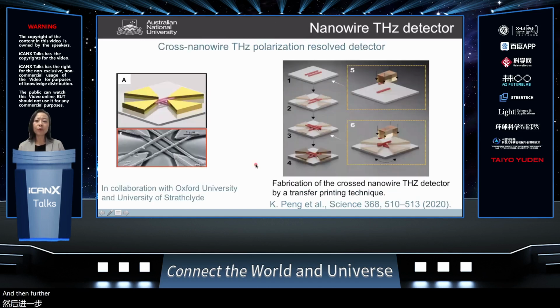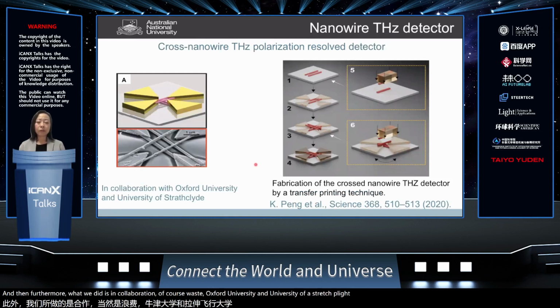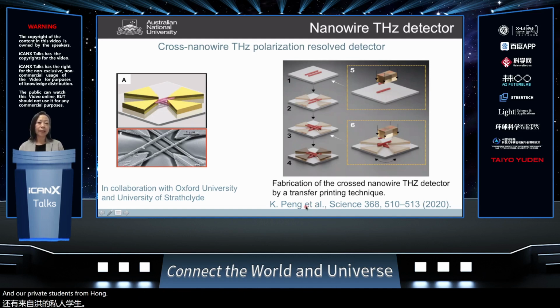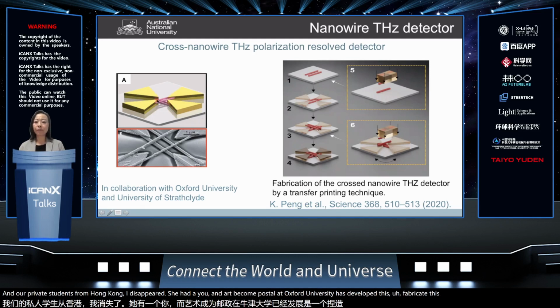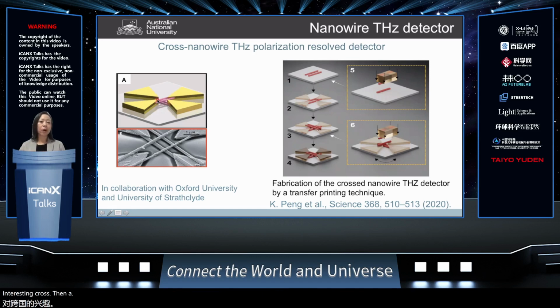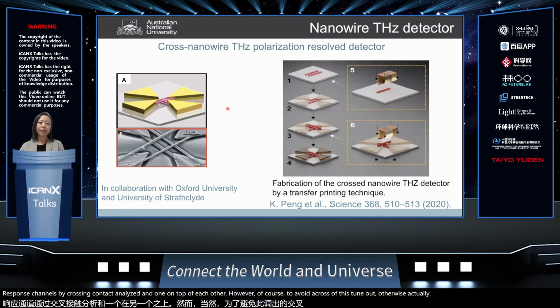And then furthermore, in collaboration with Oxford University and the University of Strathclyde, our previous student, Kun Peng, who did a PhD at ANU and then became a postdoc at Oxford University, has developed and fabricated this very interesting cross nanowire terahertz detector. So basically, it creates two response channels by crossing contact nanowires on top of each other. However, of course, to avoid crosstalk, these two nanowires are insulated from each other.